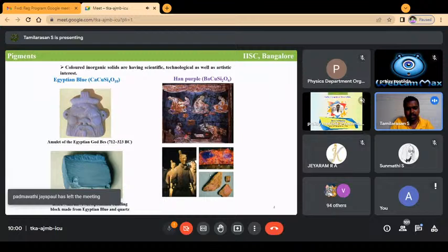We doped and we got this beautiful bright blue color. When we characterized the color, we found that the brightness of blue color for this compound is very high compared to the classical cobalt blue, which is the blue pigment used for almost several hundred years, and also the newly found compound I presented in the first part of this talk. Compared to both those compounds, the brightness of this blue color was so high, and we could publish this work in Chemistry Asian Journal.